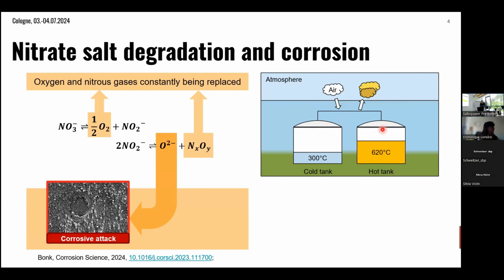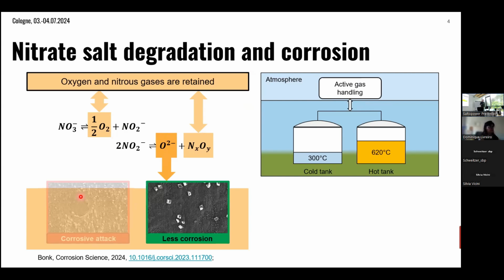So you have a phenomenon called tank breathing when you charge and discharge your tanks. Each time you charge and discharge your storage, air will come into the system, and it will also extract all or parts of the oxygen and nitrous gases to the atmosphere. This leads to a high degradation reaction at these high temperatures, producing corrosive oxides, which lead to corrosive attack on the steel. The idea is to have an active gas handling system, which keeps all the oxygen and nitrous gases in the system. This way, the equilibrium will be shifted to the left again, and fewer corrosive oxides are produced, and therefore less corrosion.